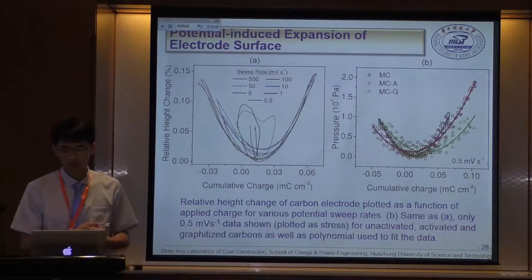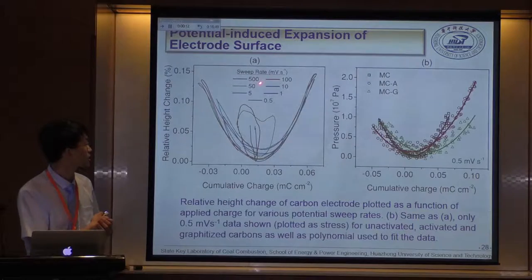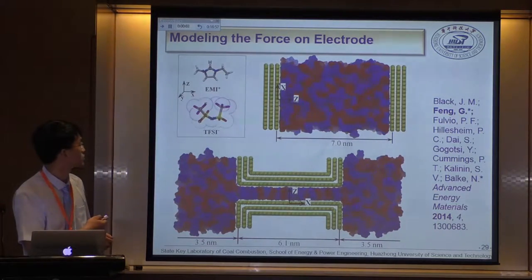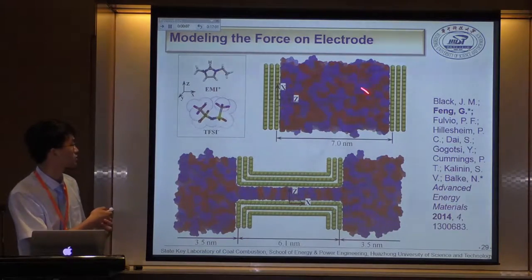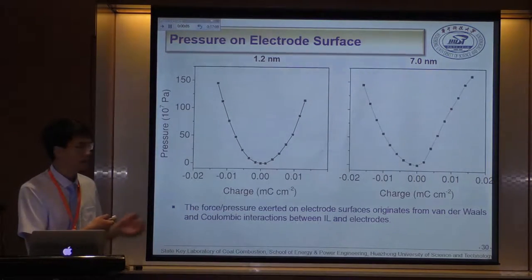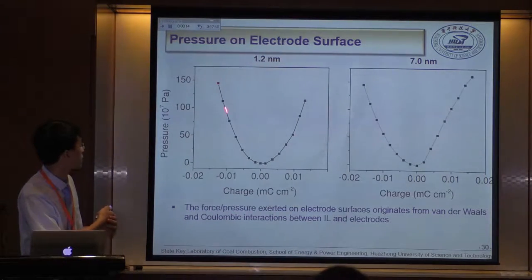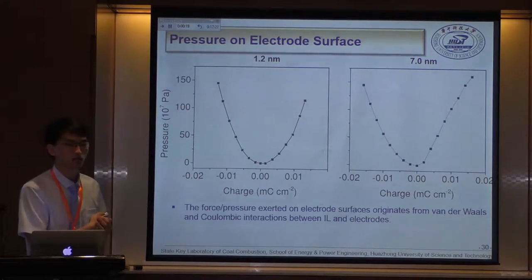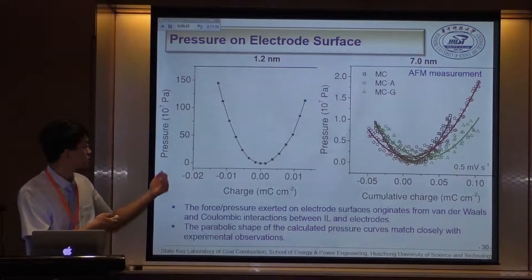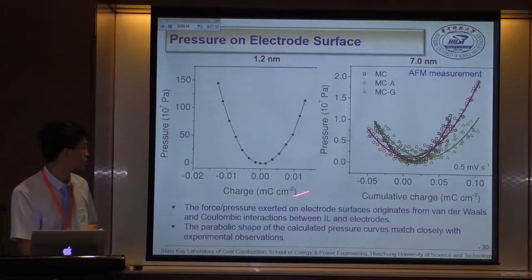In another work, our experimental collaborators found that during the charging and discharging process of a supercapacitor, the porous carbon electrode expands. To understand this phenomenon, we used molecular modeling for both small and large pore sizes. We found the same trend for both: there is a parabolic relation between the pressure on the carbon surfaces and the applied potential, consistent with the experimental data.